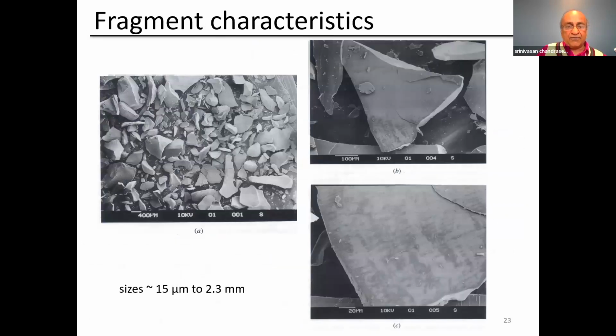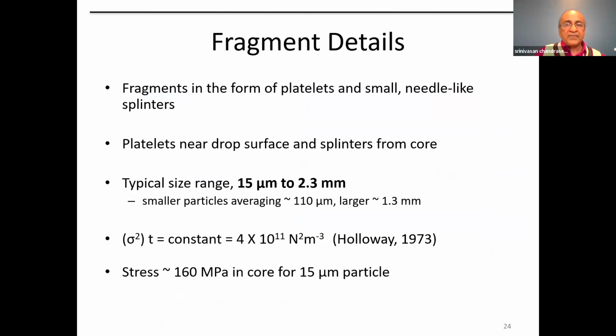Some pictures of fragments. This is less critical. We see fragments from different portions of the drop. We did experiments similar to what Holloway did by encasing the drop in glue, in an adhesive, finding out what the fragments look like at the surface versus the interior, what their ranges are, 15 microns to 2.3 millimeters or so. And we can also make some estimate of the stress in the drop from looking at the fragment sizes.